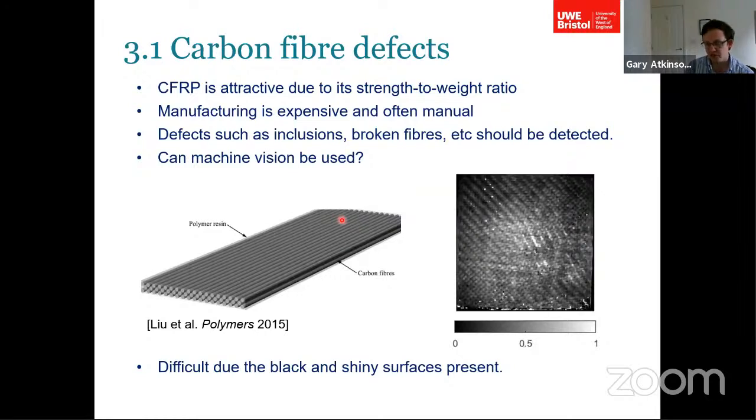What tends to happen is, if you take this surface on the left here, obviously this is not a real surface. In this synthetic case, all of the fibers are perfectly aligned. Now, if you imaged that using polarization technology and you plotted the histogram, ideally it would be flat, and then as soon as you get to the corresponding angle, you get a big sharp peak, like that. That's what you'd get in an idealized case. In practice, due to noise and other factors, you'll get a bit more of a normal distribution or something like that. But then there can also be a range of other factors.